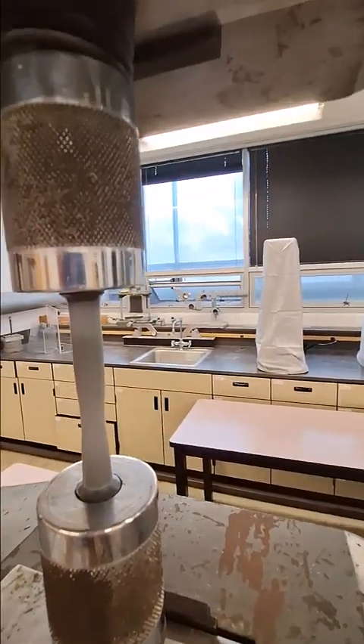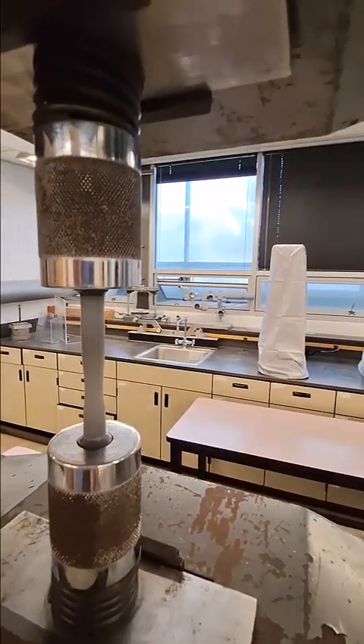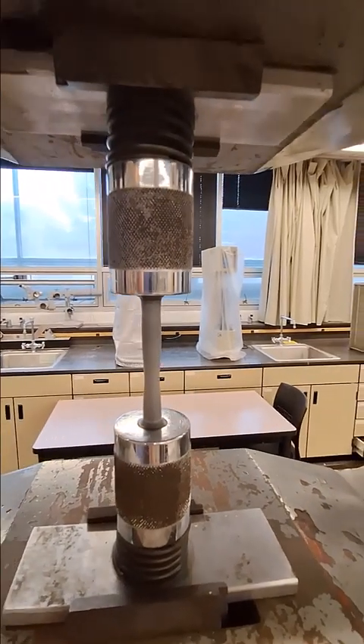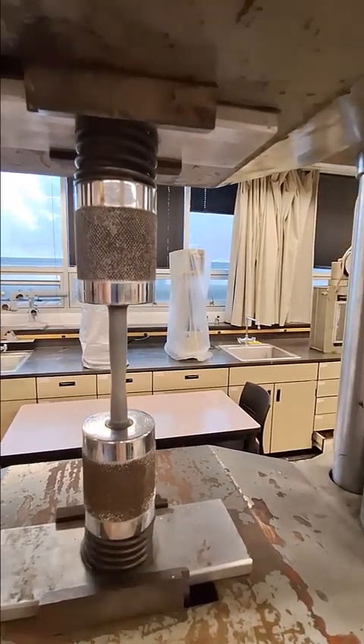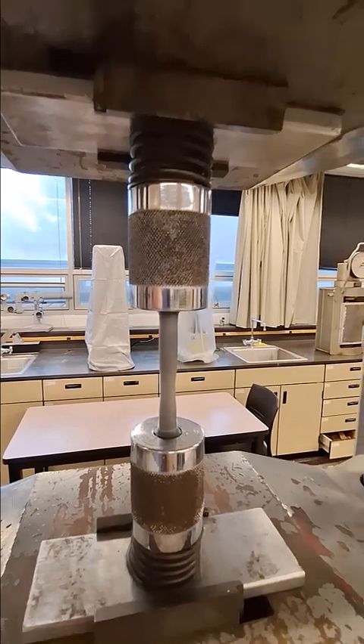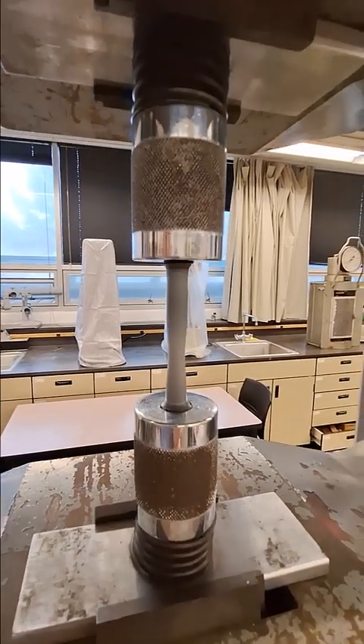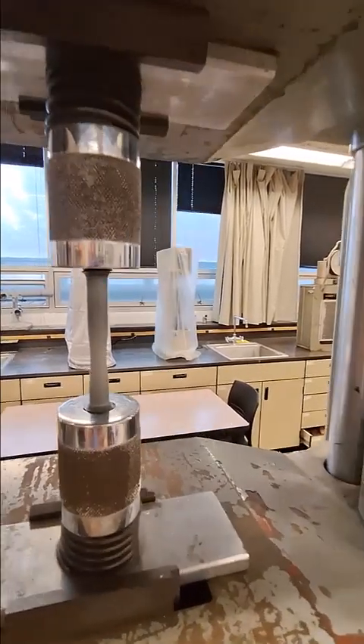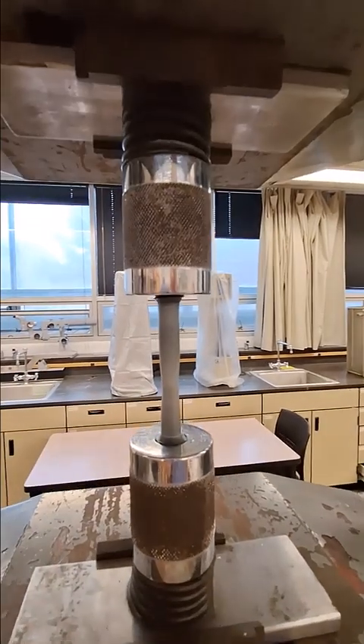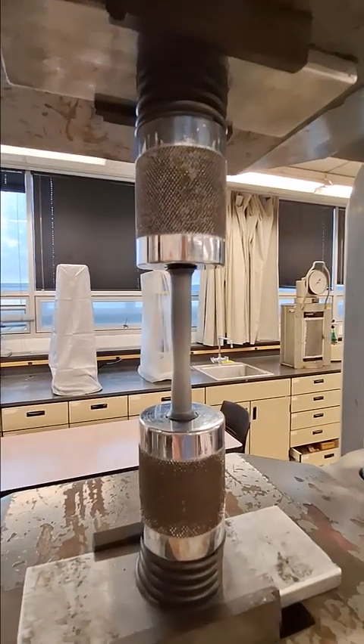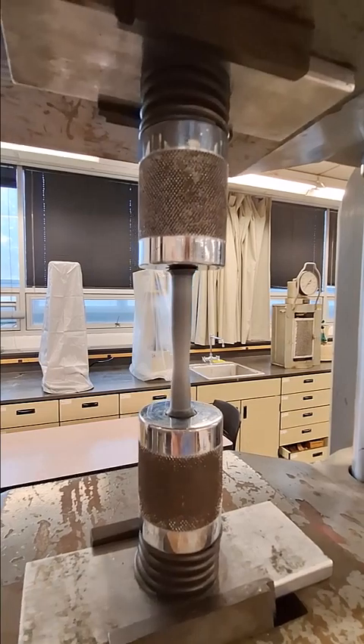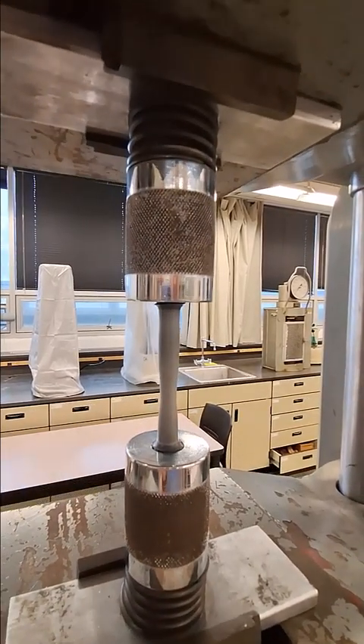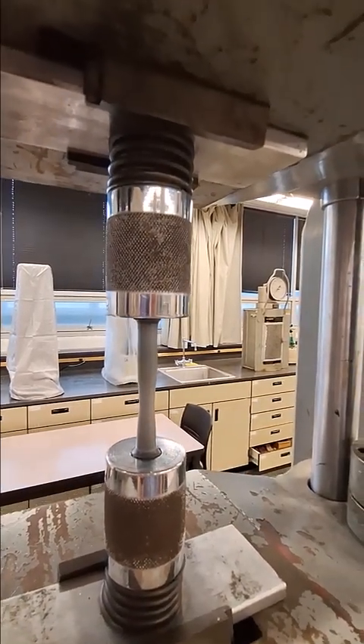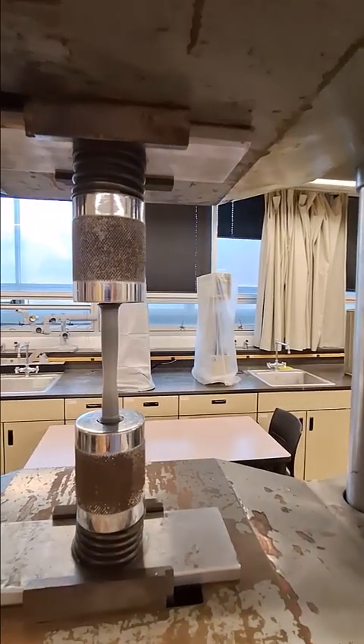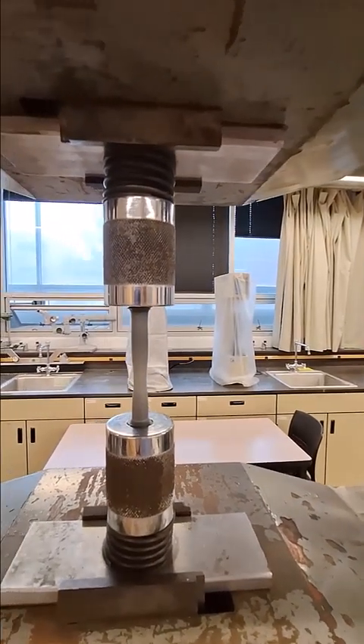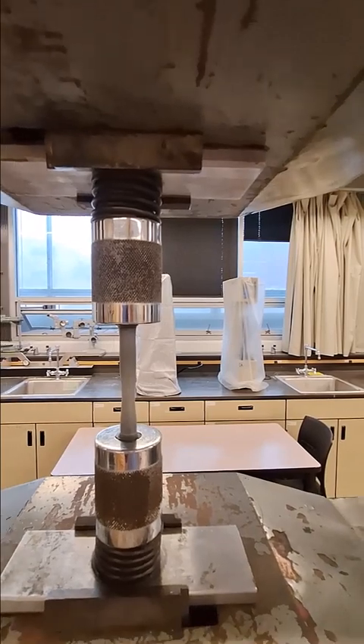But you see that change in color as well because of the chain alignment. You'll really see it once we're basically off of our sample, and you'll look at the sample in the grips. Remember, it was dark black when we first started our experiment. And you can see essentially that neck occur. We will see some fracture behavior soon, but you can see that neck.